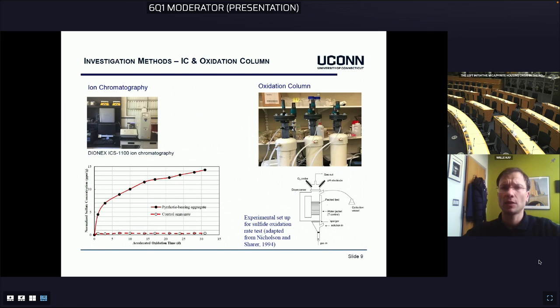On the right side is the oxidation column, which has been developed and built here at UCONN, where you see the picture in the lab, and below is the concept where packed material is put into a column, and then water is flowing through, and oxygen is bubbled through to help with the reaction rate, and then the release of sulfates in the water can be measured, and also the ion content can be measured over time. Next slide.